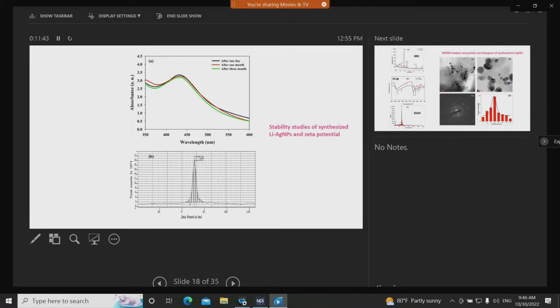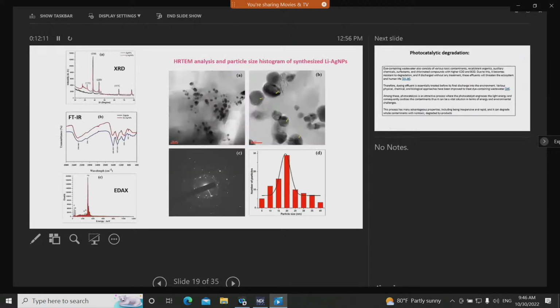In case of the zeta potential, it showed a higher negative charge, about minus 27.75 millivolts. This negative charge on the surface of the LiAgNPs suggests that the nanoparticles repel each other and prevent agglomeration. Due to this property, our synthesized LiAgNPs are suitable for long-term stability, which supports the stability results of the synthesized lignin silver nanoparticles.